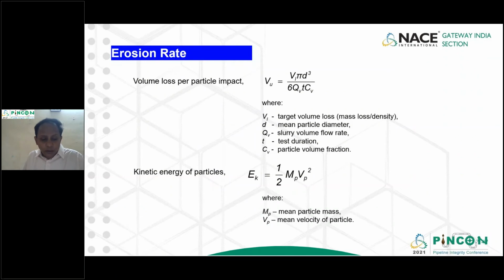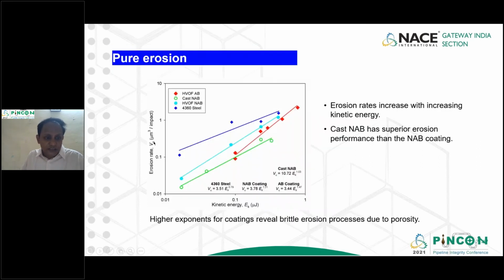Then I come to erosion. For corrosion, we talk about a corrosion rate that is just millimeter per year. But when it comes to erosion rate, when I use sand particles, I use another equation, because I'm talking about the flow rate of the liquid and then the sand particles. That is nothing but the slurry which is forming, and the slurry has a size of 135 to 235 micron. So I look into the kinetic energy. All these parameters I take and formulate a new equation which we call the volume loss per particle impact.